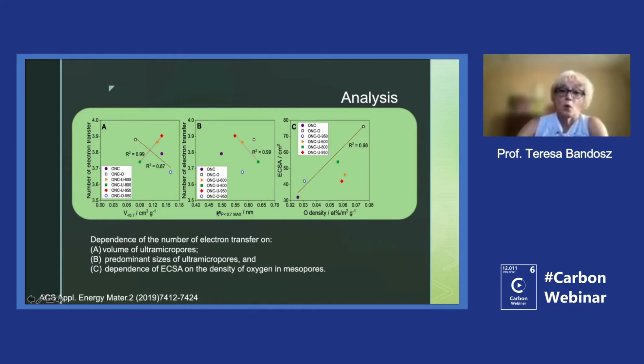And on the other hand, when we look for the dependence of n on that maximum of the peak, the good linear dependence was only for the carbons with nitrogen. So it looks like here the situation is more complex.